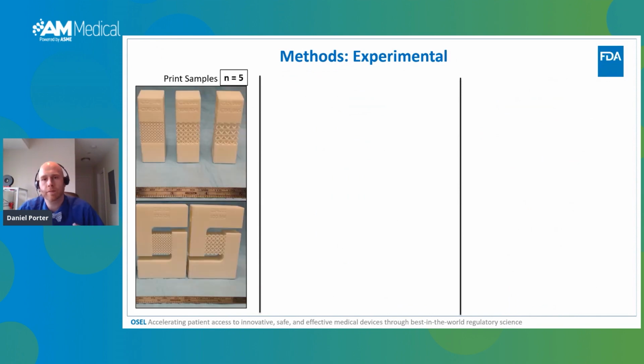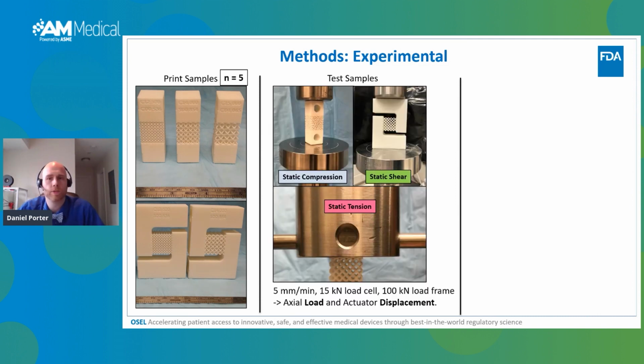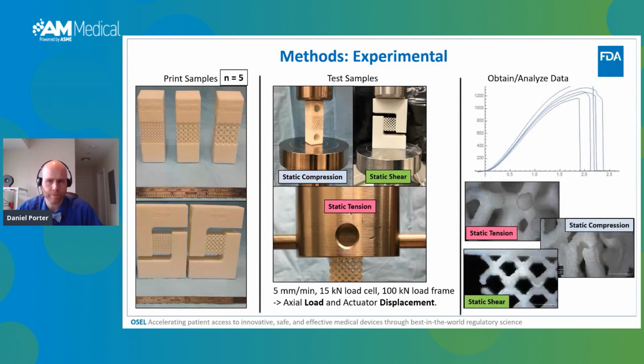The experimental method section is actually quite simple. So we fabricate and print all of our lattice samples. We're going to test 5 from each lot. We're going to take them to a servo hydraulic load frame, and we're going to test in compression, shear, and tension. The actuator moves at 5 millimeters per minute. We use a 15 kilonewton load cell, and we record axial load and actuator displacement. We obtain the data. We do take images of some of the failure surfaces and the failure modes using a high resolution microscope. I won't go into too many of those images due to time.